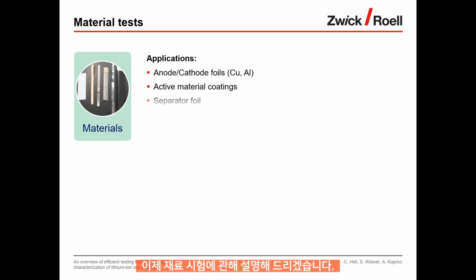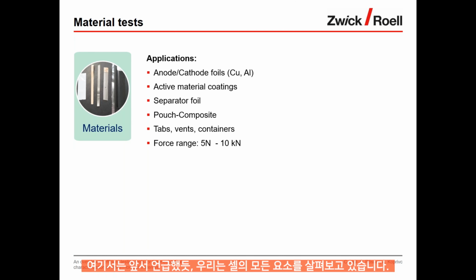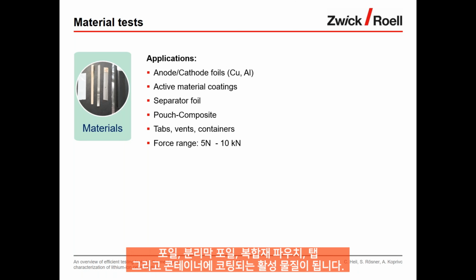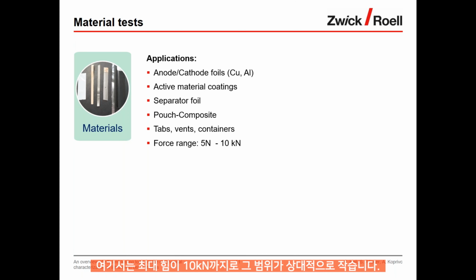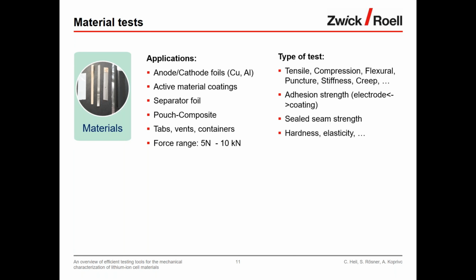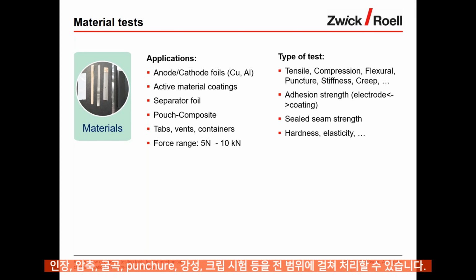Okay, and then we come to the materials test. So here, as mentioned before, we're looking at all the elements of a cell, the anodes, the cathodes, the foil material, the active material that is being coated onto the foils, separator foil, the pouch composites, tabs, vents, the containers. And here we typically look at smaller forces ranging up to about 10 kilonewton. So here we cover the full range of tests that we can do with our mechanical testing machines: tensile, compression, flexural, puncture, stiffness, creep, and so on.